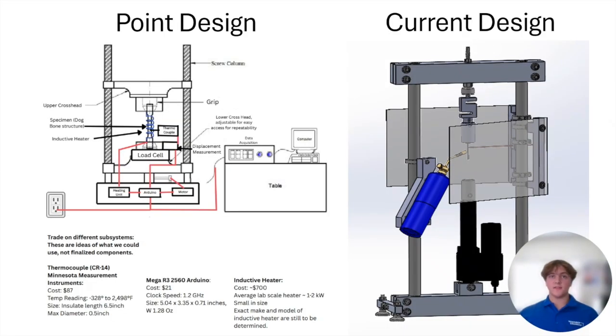This segment shows how the original point design directly drove the final system. Early on, the main design elements were the heating system, the temperature measurement device, and the controller, because those were the components most closely tied to the major project goals. From the beginning, we needed a system that stayed under 200 pounds, operated from 120 volts, heated the sample to 2000 degrees in 10 seconds, and applied over 1,000 pounds of tensile load while displaying live test data.